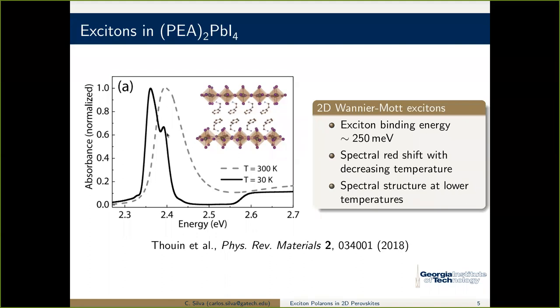And what I'm going to argue is that these are different exciton polarons, that the exciton binding energy is different for different excitons, because of the way that they couple to the lattice, the way that the lattice dresses them, is distinct. So the binding energy is not only, as in a standard Wannier exciton model, the Coulomb interactions between electron and hole, but of course between all of the ions in the crystal. And so you have to put into your system Hamiltonian the electron and hole couplings, as well as couplings to all of the ions in the system. And the exciton polaron is an eigenstate of the system. It's not that you excite an exciton and it feels the lattice and you form a polaron. The exciton polaron, the way we see it, is an eigenstate of the system.